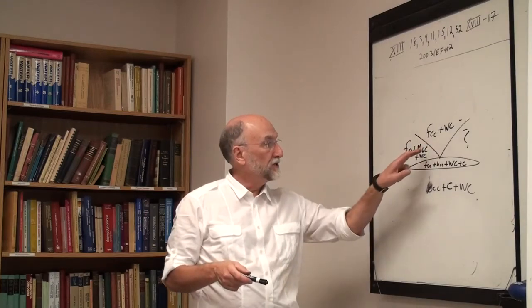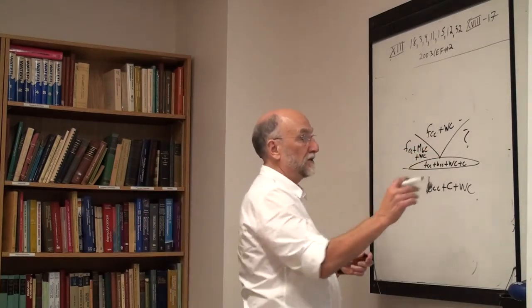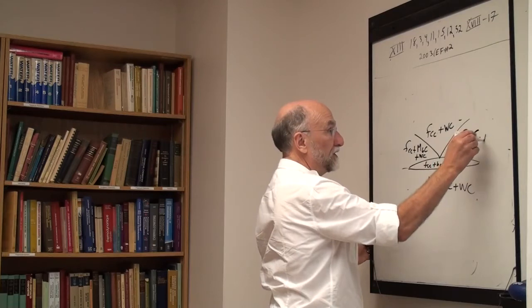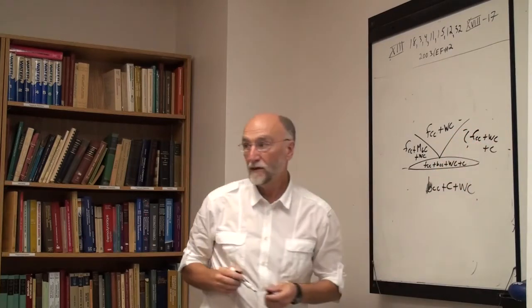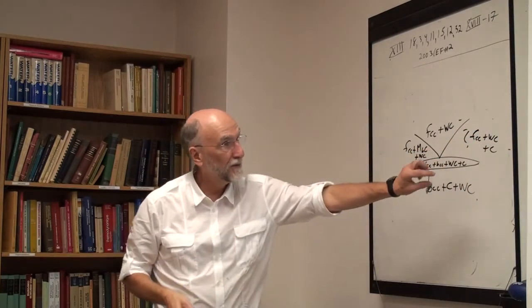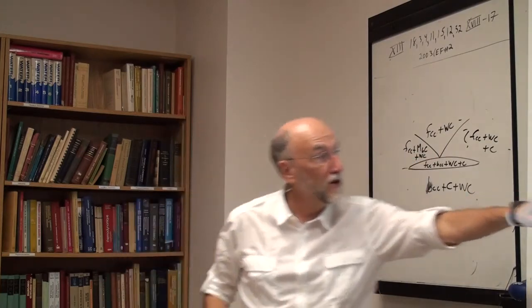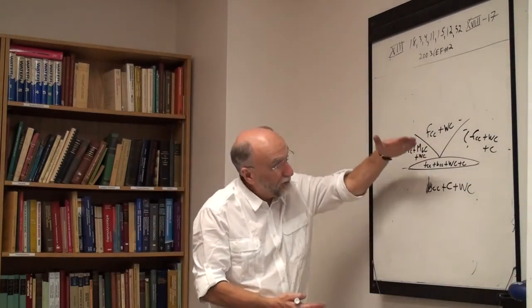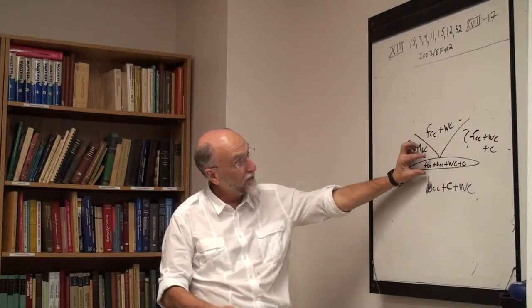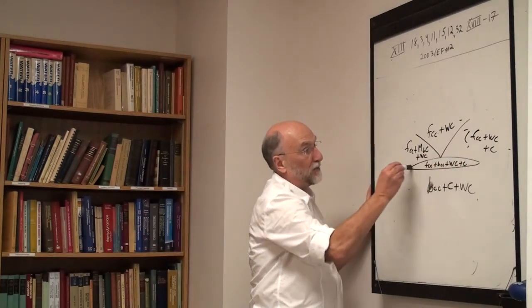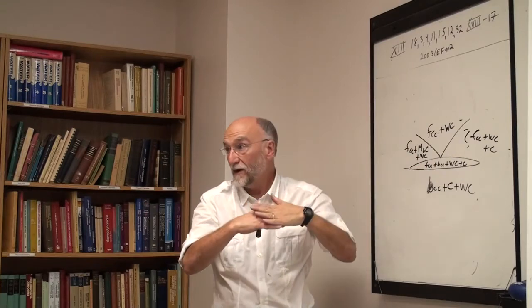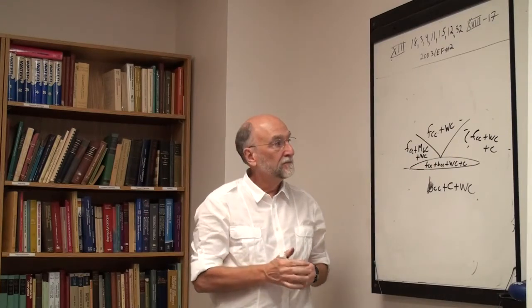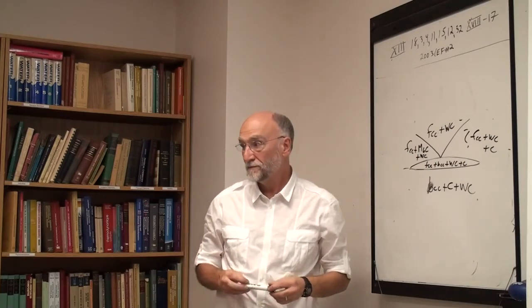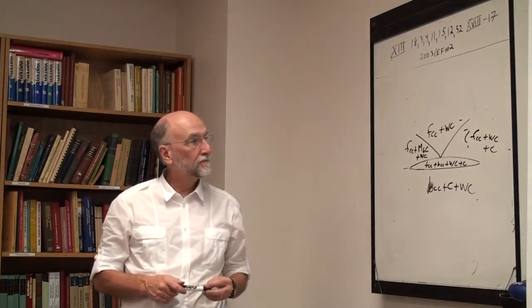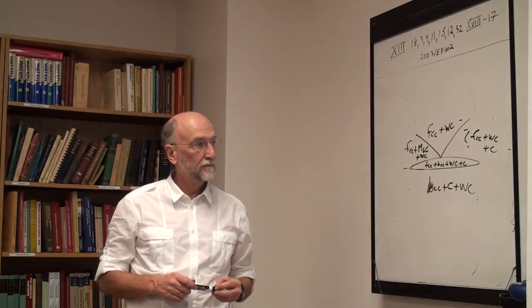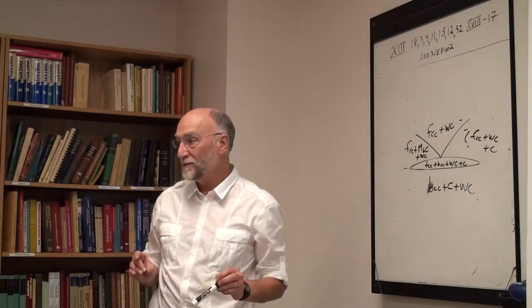Okay, so you get your two-phase region, three-phase, four-phase. So clearly over here then you have FCC plus WC plus carbon around this point here. So this is not a node. You've got to spread out the four-phase region. This is your opened up four-phase region. In actual fact, the upper boundary and the lower boundary are coincident. Everybody happy with that?